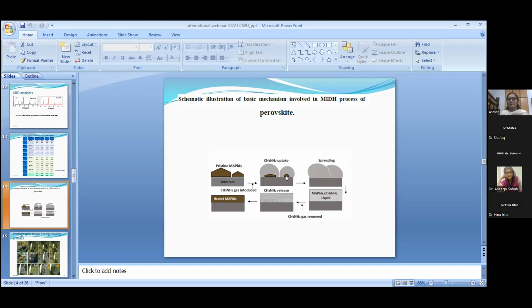So the simple phenomenon of the healing is upon the exposure. This is the schematic illustration of the healing process. Upon the exposure of the methylamine gas, first the perovskite crystal is dissolved in a liquid state, which is colorless. And after degassing, when we remove the methylamine gas, the crystallization of the perovskite starts again, and we get a very nice brown color of the perovskite layer.